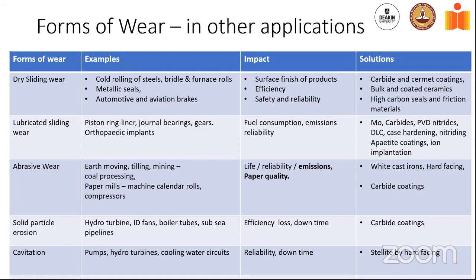But if you start looking at the vehicles that are produced all the way from the early 90s through now, every car that you buy essentially has a bright, beautiful, glossy finish. And that's because the cold roll steel goes through all these rollers at a speed of around 35 to 50 meters per second, goes to rollers and gets annealed at maybe 850 to 1000 degrees Celsius. But you really have protective coatings on all the roll surfaces to ensure that the steel strip has a bright surface finish.